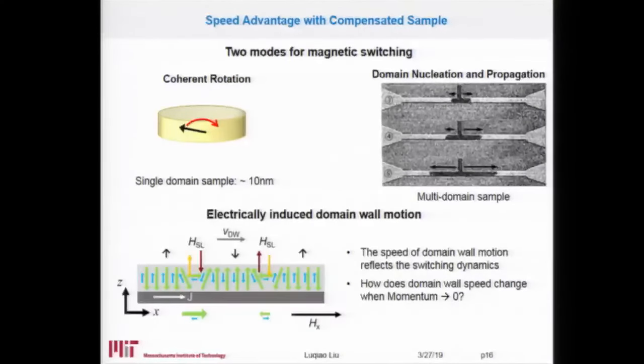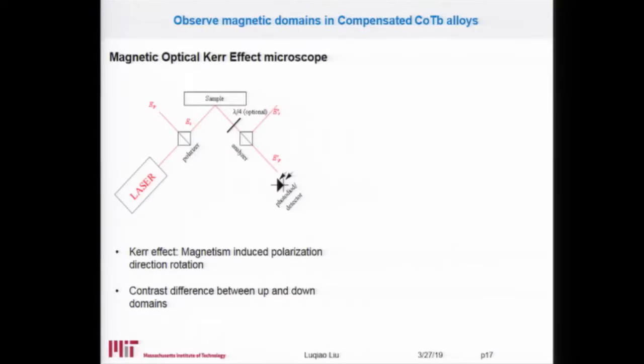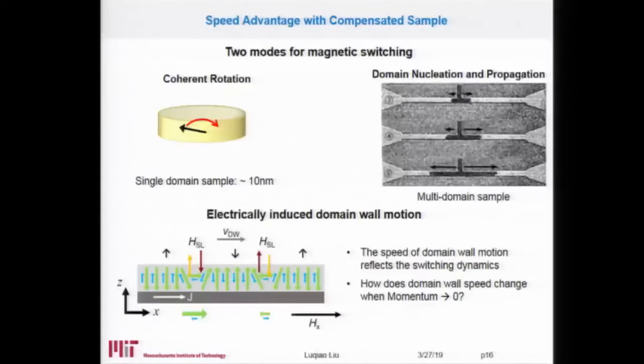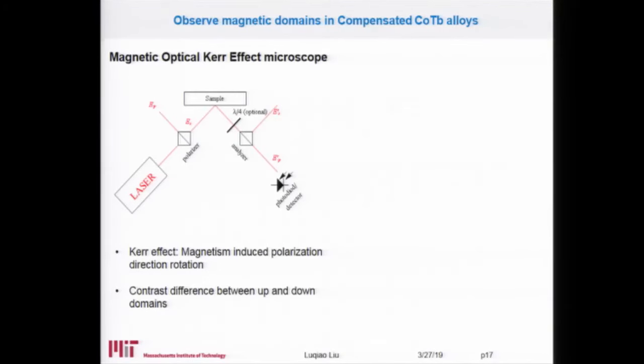So basically what we do is we utilize the same spin Hall effect, the electrically induced magnetic switching mechanism, not to switch the moment altogether, but to push the magnetic domain wall. So basically, if we can show that the magnetic domain wall moves at a faster speed compared with the previous magnetic materials, then we can also potentially argue that those zero moment magnets do have faster switching speed. So how do we observe those magnetic domains? The method that we utilize here is a magneto-optical Kerr effect microscope.